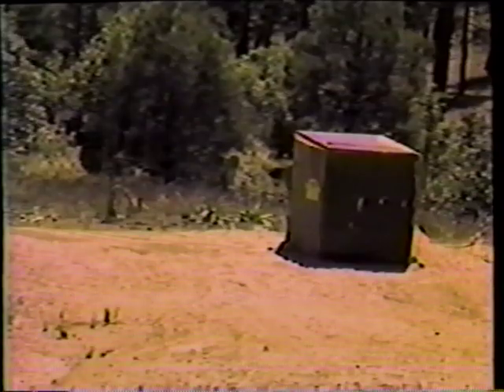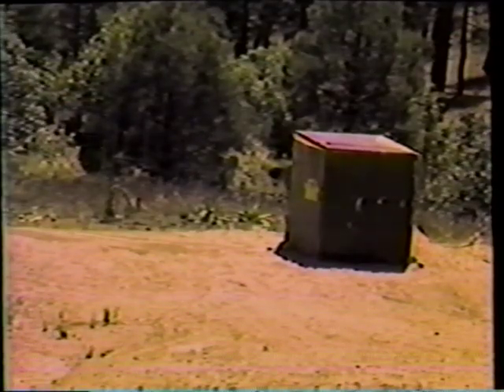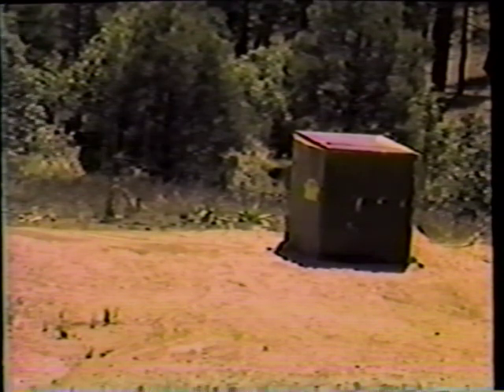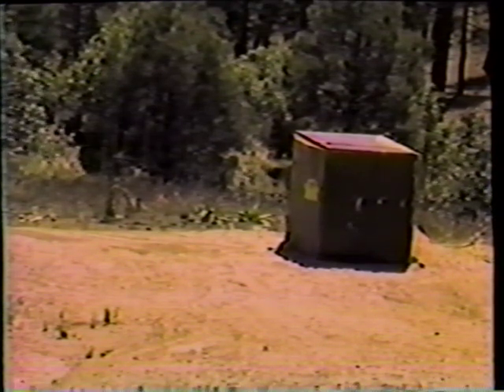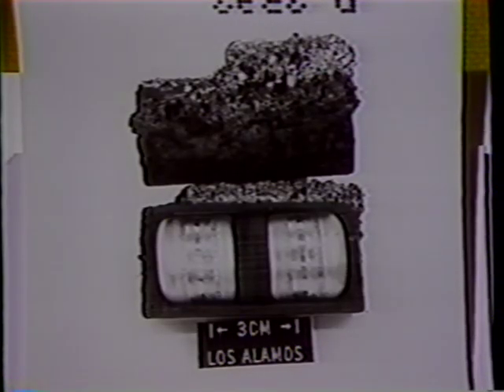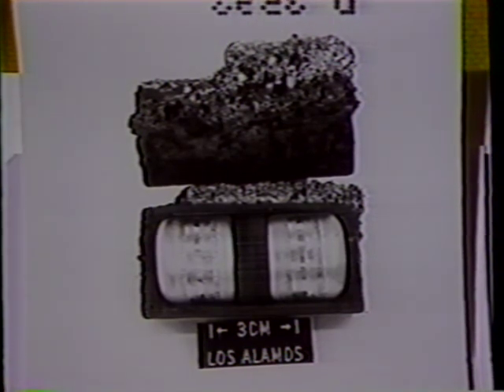If a launch vehicle explodes on or near the launch pad, it may produce fires from the burning of any residual propellants. One of the most severe of these fires would result from the burning of the solid propellant used in the Titan Centaur boosters. To simulate such a condition, 2 specimens, a bare fuel capsule and 2 capsules in an impact shell, were placed next to the maximum quantity of Titan solid propellant, a cube 3 feet on each side. The propellant was ignited, producing a violent flame zone about 15 feet long with temperatures above 3,700 degrees Fahrenheit. The results of the test showed that exposure to this severe fire would not cause any release of fuel.